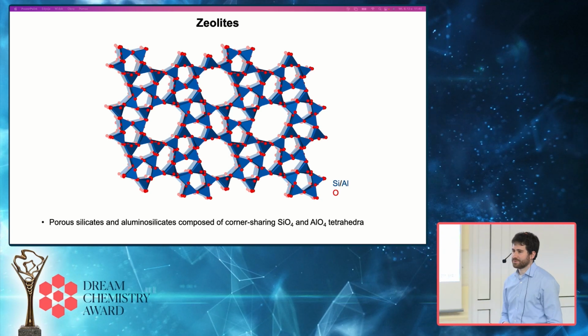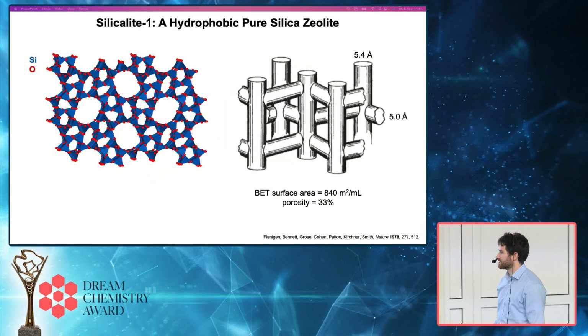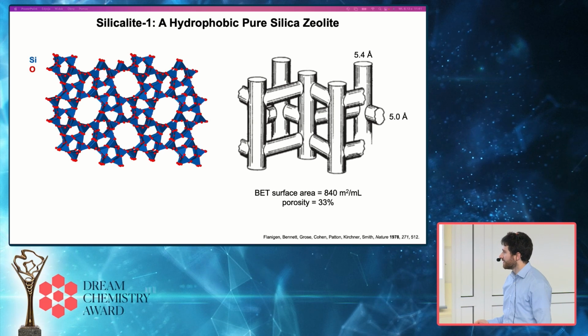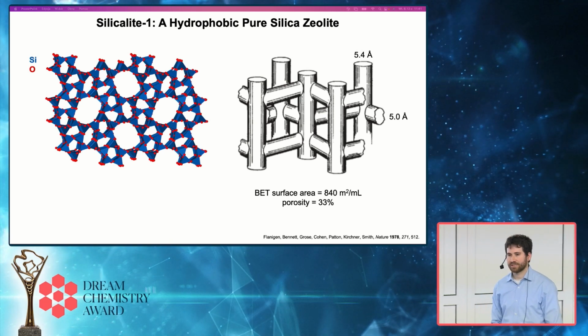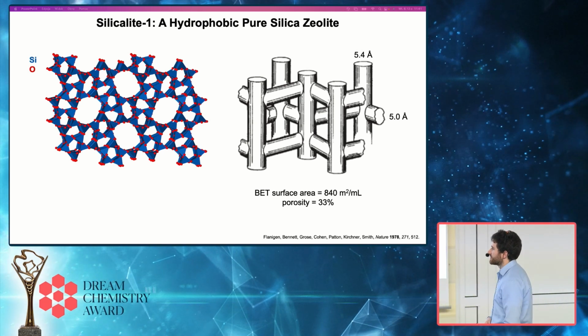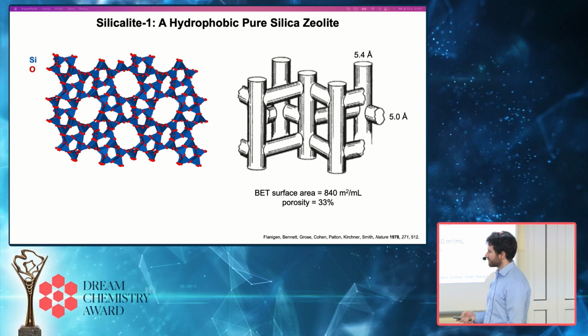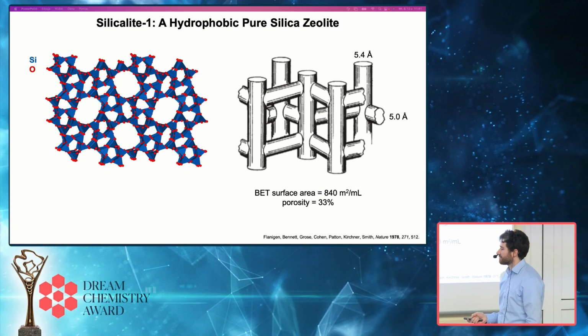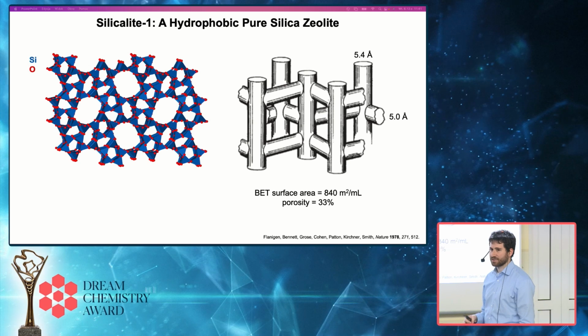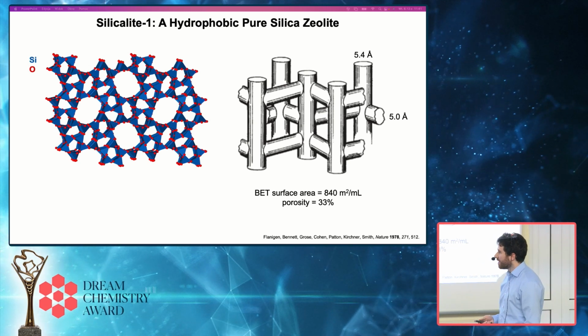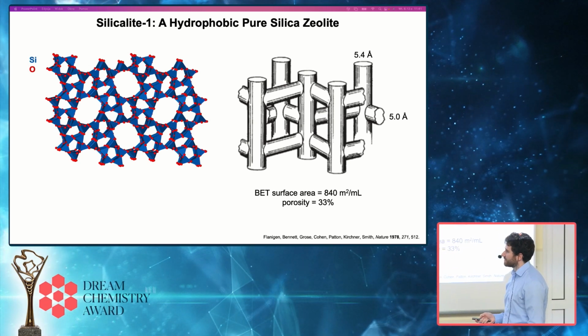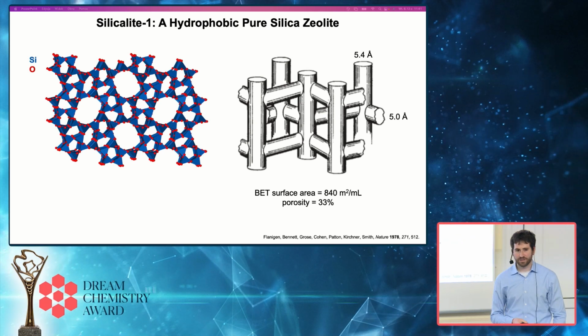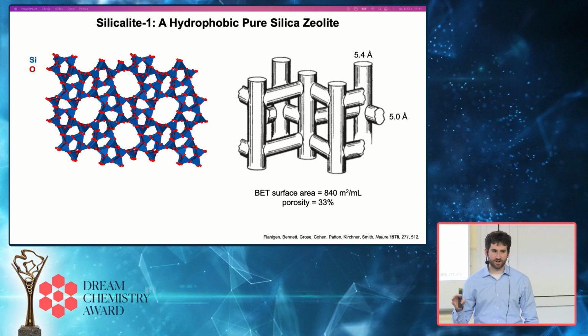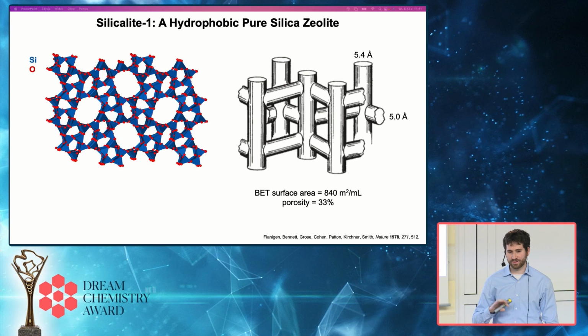The particular zeolite that we started working with is known as silicalite-1. This is a rather old zeolite that was first synthesized in the 1970s. The reason we were interested in this particular zeolite was, one, that it has quite a high surface area. It's about a third empty space, so a very porous material. But even more importantly, these silicon-oxygen bonds are quite nonpolar, and the internal surface of this zeolite looks very much like that of an activated carbon, so it's very hydrophobic.